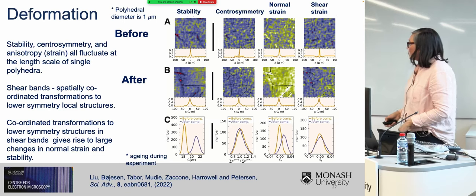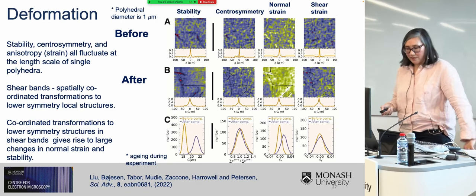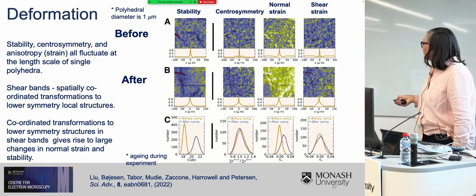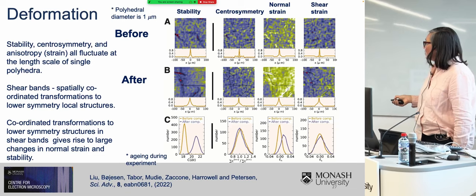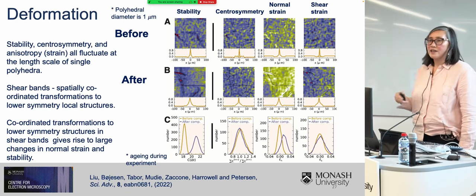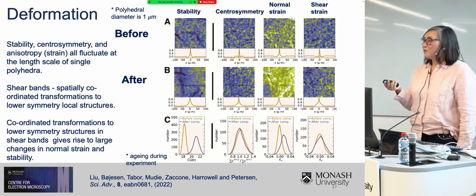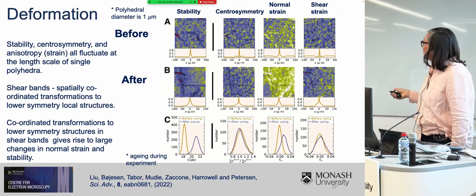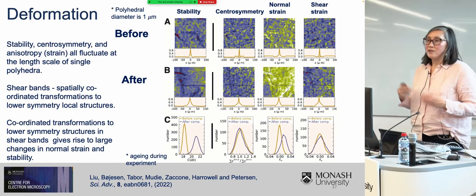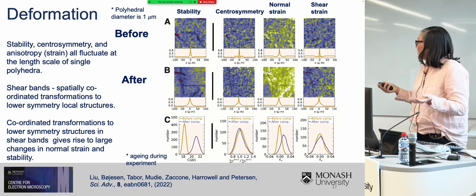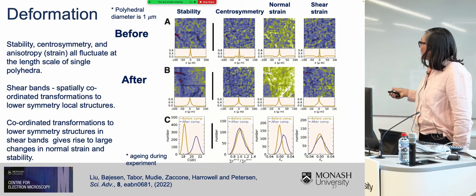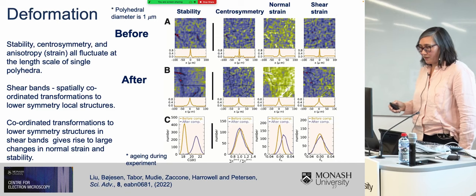But I think what I find surprising, and what I found surprising when I first unpacked this data set, is that the change in the local centrosymmetry before and after compression, the decrease, is incredibly small given that in the shear bands we have this enormous increase in the normal strain. And I think the only way you can understand that is by noting that really we're having very coordinated local transformations to lower symmetry structures inside the shear band areas.